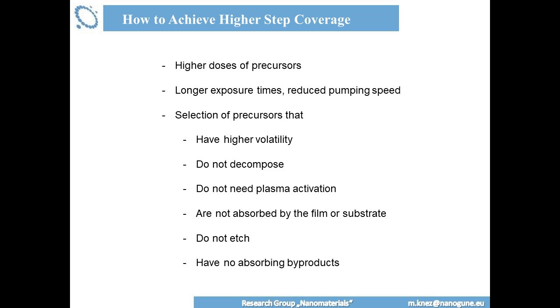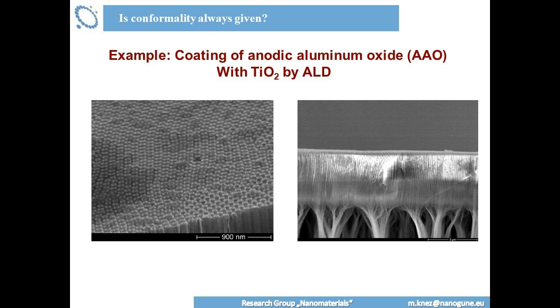And you should not have absorbing byproducts. And this is a very, very important issue because it's sometimes misleading, and I'm sorry to go back. Here. If you see such a structure, here, for example, with titanium oxide, you say, my dose of the precursor, or the exposure time, was too short. That would be the natural conclusion out of this image. So, again, what we did here is, we had porous alumina, we coated with titanium oxide, this is the structure from the top. Then we etched selectively away the aluminum oxide, partly. So this is the remaining aluminum oxide here, and the titanium oxide is here. You would naturally say, okay, this is too short exposure time.